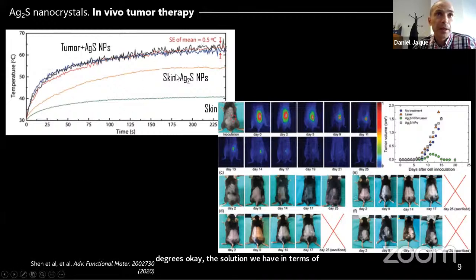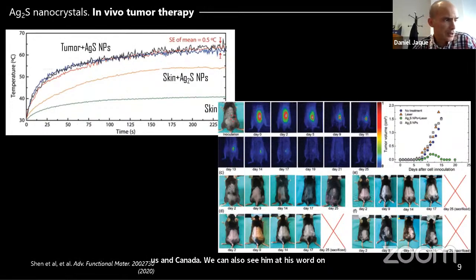When we repeat the same experiment without nanoparticles, by looking at the surface temperature with a thermal camera, we can also see the heating, but it's lower than the temperature inside the tumor. That's something that was expected.